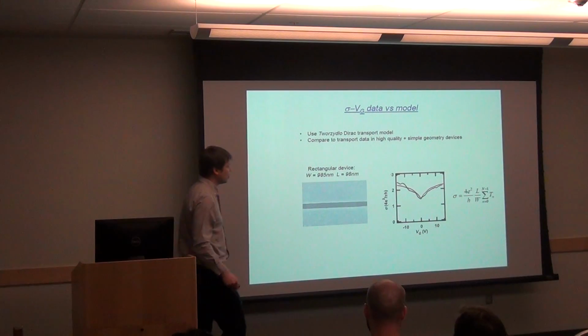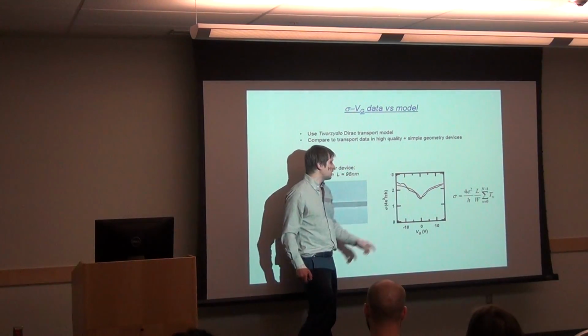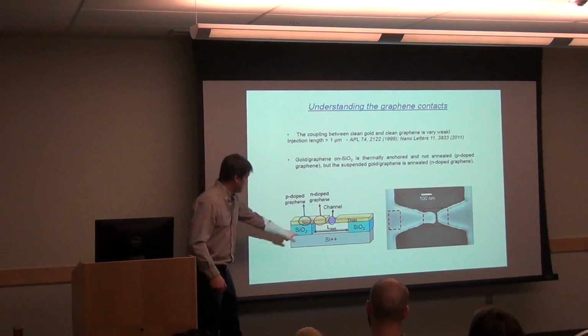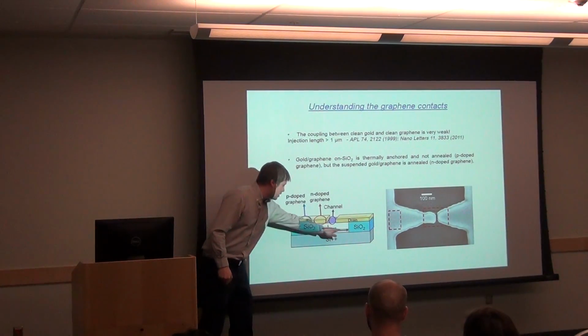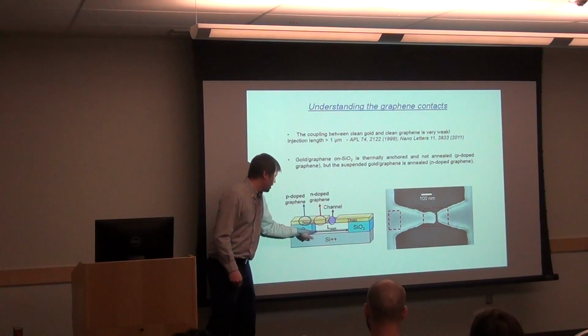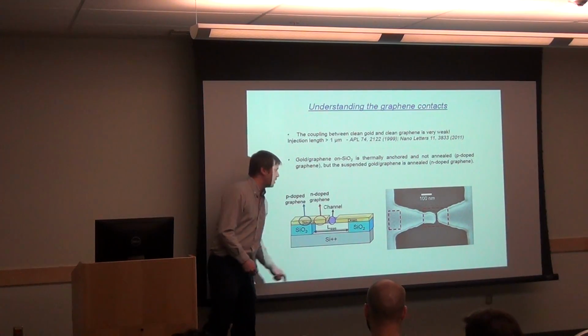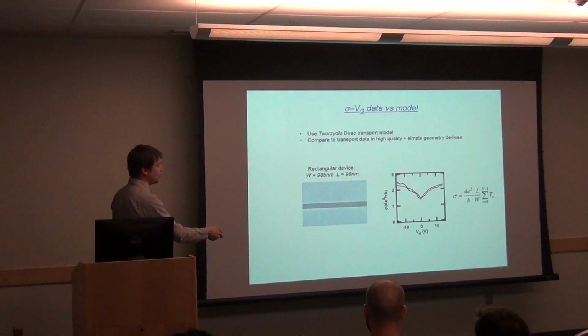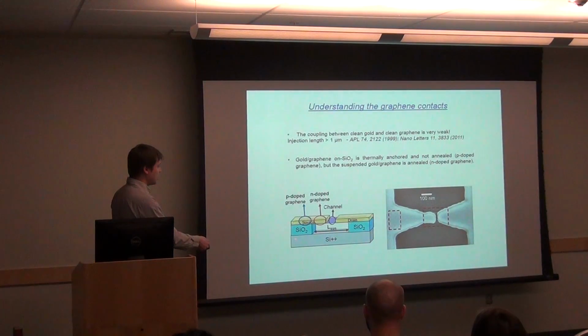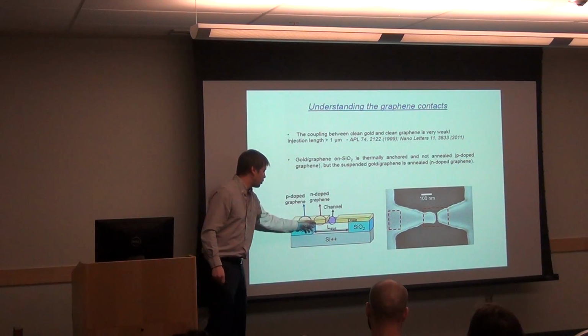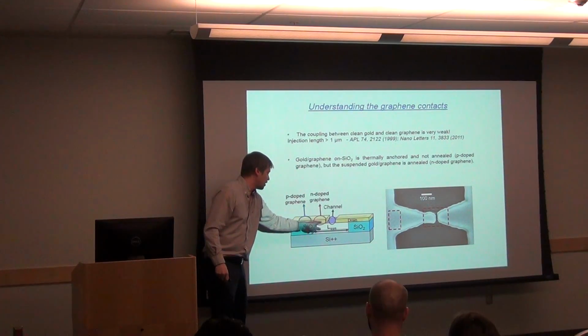You see there are additional bumps in the measurement. But we already understand those because they are not from the channel, they're from the contacts. Remember, the contacts are also ballistic, and when the electrons bounce back and forth, they create interference fringes. And those are these fringes. If you measure the spacing between them, they actually give you this length. You can tell that these contacts are annealed because if you look at the texture, the gold film texture is different. Here the gold is really annealed, and here it's not. It's simply because this is not thermally anchored. So when we flow a big current in the device, this gets hot. This doesn't get hot.